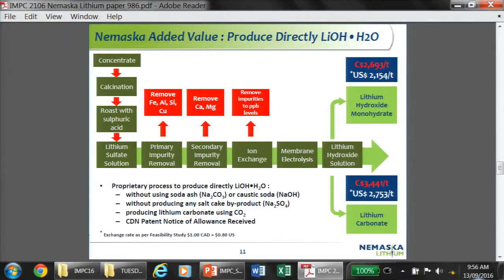Yes, I can briefly comment. This kind of electromembrane process, or membrane electrolysis, uses a titanium coated anode. In that case, you need to use what you call a DSA, dimensionally stable anode, DSA-O2, to evolve oxygen instead. In the chloralkali industry, you use a DSA-Cl2 anode; in our case it's a DSA-O2 anode. It's a similar composition to the chloralkali industry, but not exactly the same.